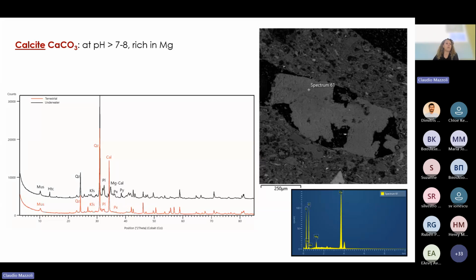Right. We can detect this obviously also from the diffraction point of view. For instance, here there's an example of ceramic taken from the same type of material. They are amphoras, and some of them were found on land in the production sites, and others were discovered in a cargo, which experienced almost 18 centuries in underwater environments. And we can clearly see that in the materials which stayed long underwater, there's a crystallization of calcite that is not present in the one that we have from the land. So we compare the same material from two different situations, but obviously they differ in mineralogy.